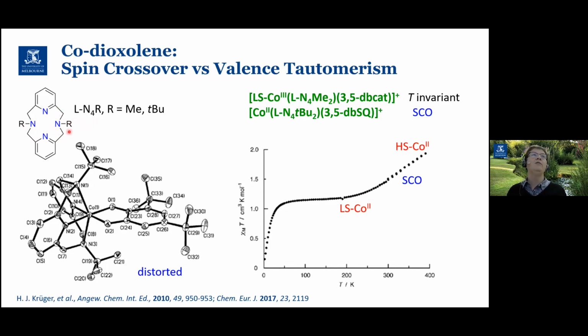So an analogue where you have a methyl substituent on the amine groups of the ligand and another analogue where you have a tertbutyl substituent. In the case of the methyl, the molecule exists in the cobalt-3 catechol charge distribution at all temperatures with no spin crossover or valence tautomerism.